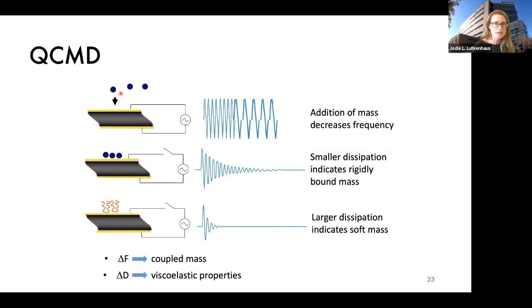If we add some material to that crystal, the frequency of the oscillation will slow down because of the mass. And if we measure the change in frequency, then we can use some viscoelastic modeling to actually estimate what that mass was. And then with dissipation monitoring, we can monitor how the signal decays or dissipates, and we can get a sense of if the polymer electrode is rigid or soft, and in some cases we could even model the shear modulus with viscoelastic modeling.